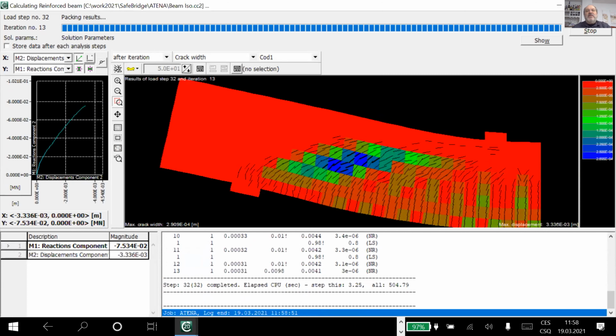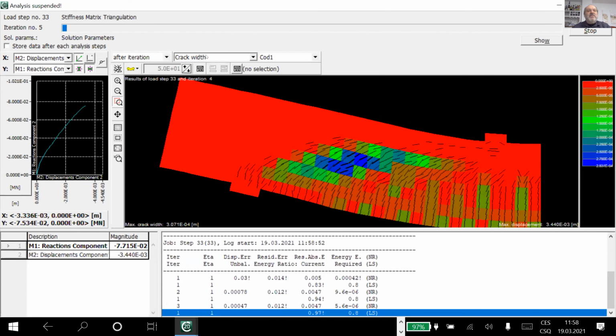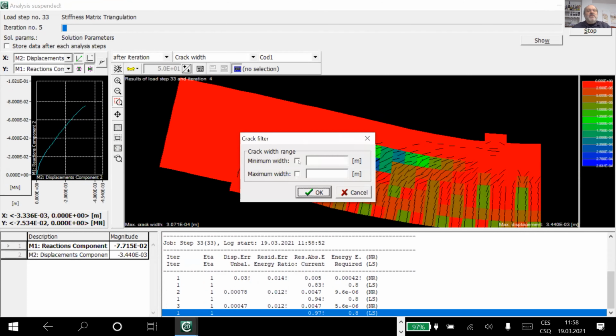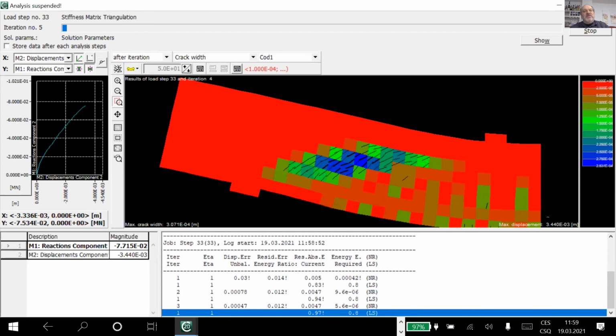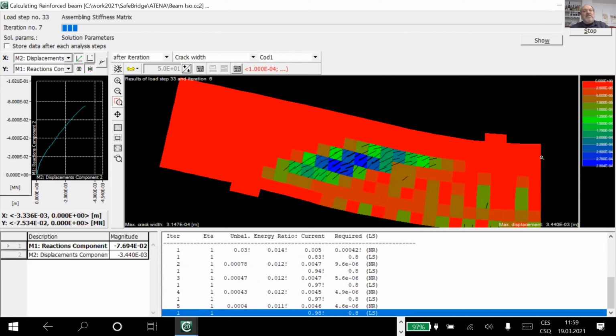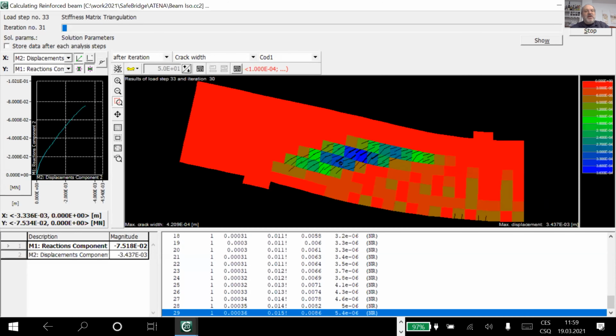We can again make the filtering to reduce. We can put there, for example, 0.0001. And you see the bending cracks are already smaller than our limit, but the shear cracks are increasing.